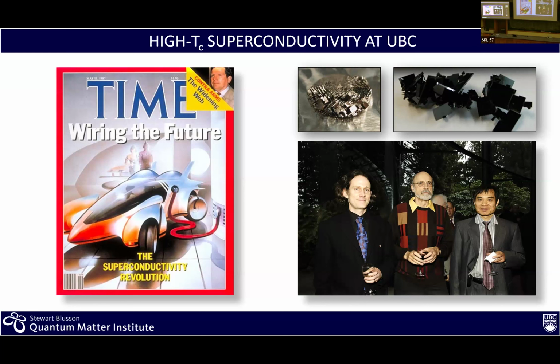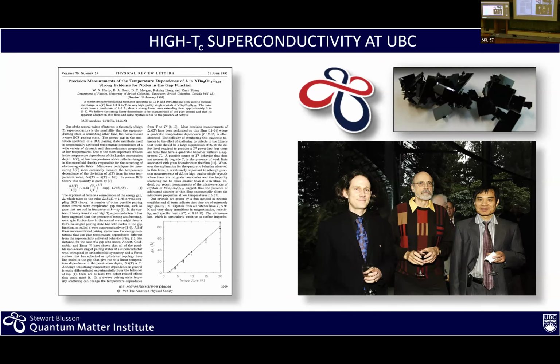And what they were after was growing this high purity crystal. This is yttrium barium copper oxide. So really their effort was to grow the purest samples of this material to do a very specific experiment. The experiment had to do with measuring the microwave penetration depth in the material and being able to distinguish between a pairing or an interaction in this system having a node or not having a node. Basically, as a function of temperature, seeing whether you could detect a linear behavior, or an activated behavior for an isotropic S-wave gap.